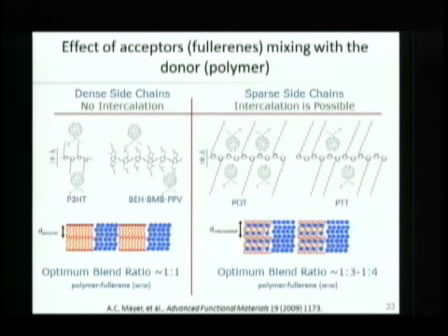And if the fullerenes go in between those side chains, then you get these mixed phases, and it turns out they're only good at transporting holes, and so if that's all we have, we don't have a way to get electrons out. And so we need to have plenty of fullerenes so that we can fill in all those spaces between the side chain and still have fullerenes left over to form a pathway for the electrons. And so if the fullerenes go between the side chain, we need a lot of fullerene. We need about 75% of the film to be fullerene.